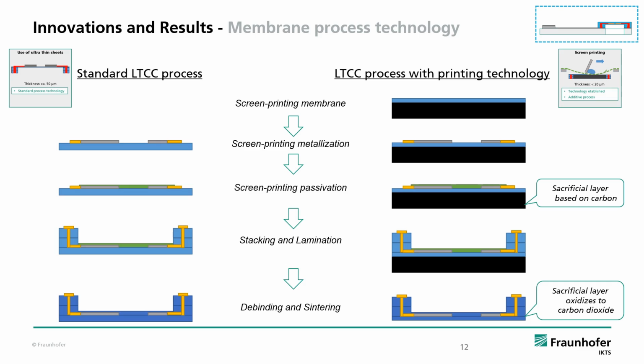The membrane is screen printed onto the carrier, the sacrificial layer based on carbon. And after that, the metallization and the passivation can be printed onto the membrane via screen printing. Stacking and laminating follows, and the fabrication process finishes with the sintering process. The sintering process is adapted so that the sacrificial layer has time to burn out.